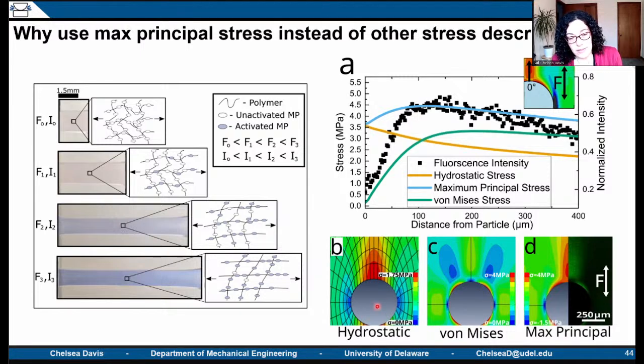Others are thinking deeply about this. We started out with hydrostatic stress. That was not great because we didn't allow any shear to be incorporated into our material. And you can see that it does not have the same shape as what we observe in our real experiments. So to end a really long answer, we settled on max principal stress as our stress scalar that we're using for our magnitudes because we allowed the stress tensor to rotate. And that was the best way we could think of to incorporate the shear stress effects and get something that semi-quantitatively matched really well with what we were observing in our experiments.